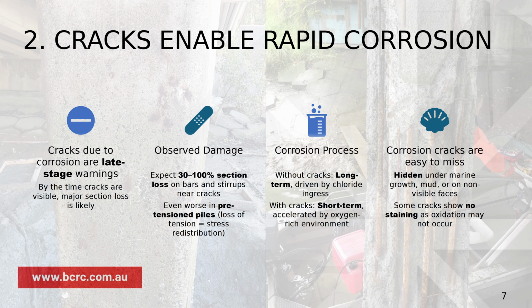And it's even worse for pretension reinforcement, because once we get the strand failed, it leads to a redistribution of forces in the entire element, which could lead to various consequences. I would like to simplify here a bit, but without cracks we're dealing with a long-term corrosion, because it's driven by chloride ingress and corrosion takes off very slowly.